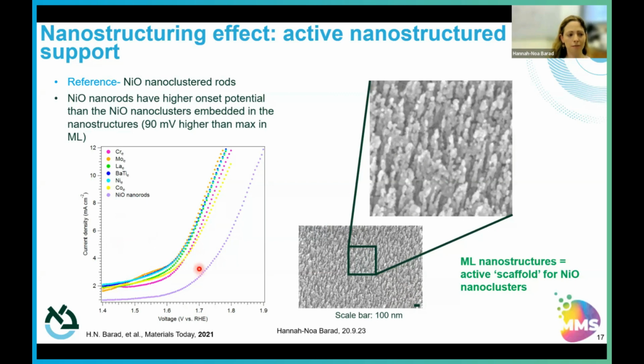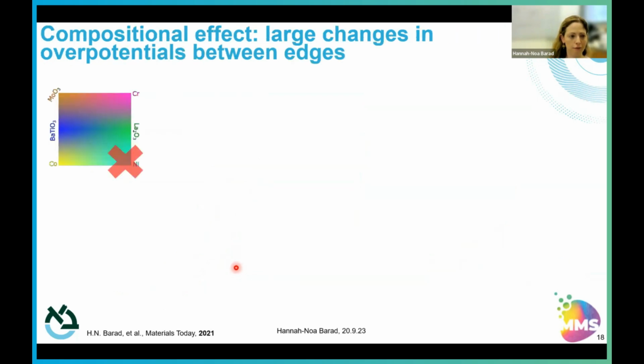So this is significant. And what we understood from this is that even though we have nickel oxide as the source, it's actually the nickel oxide nanoclusters that are embedded within our nanostructures which allow this ability for much better activity. So if we just have pure nickel oxide nanoclusters in nickel oxide nanorods, they're not as active as the ones embedded in this special nanoscaffold.